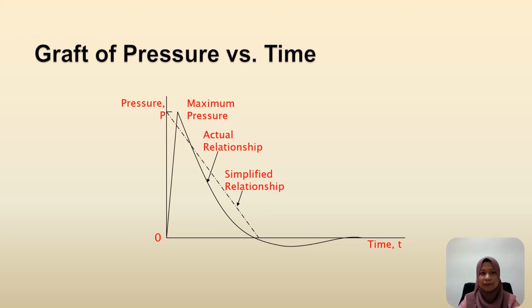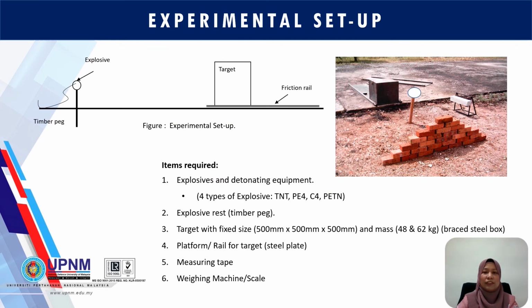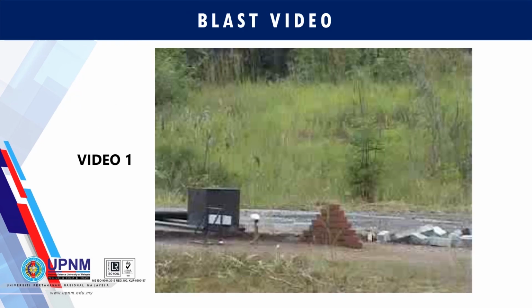This figure shows how we set up our experiment. As you can see here, the explosive will be placed on a timber peg, and the target, a steel box, is placed on a steel plate with a known friction coefficient, acting as a friction rail for the target. The explosion will cause displacement of the target due to the pressure exerted on it. So both the displacement and the pressure are variables that we need to determine. This is the video that was taken during the blast test.